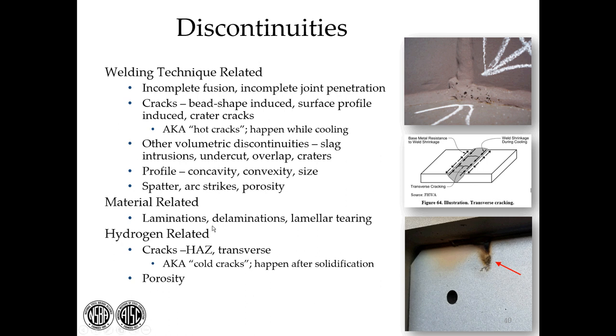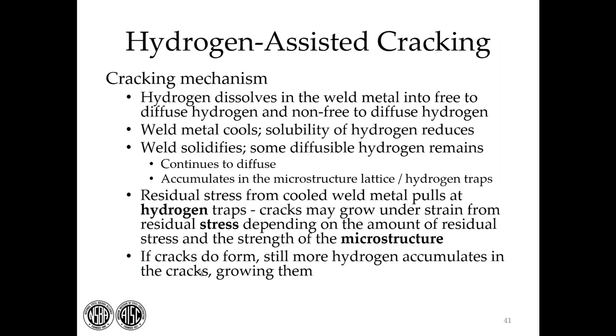And then finally, you have hydrogen-related problems, which can be porosity. Porosity can be from hydrogen. It can also be from other materials. You see it up here in welding technique as well. And then also hydrogen cracks, which are known as cold cracks. So hydrogen is a particular concern in welding. A lot of the practices in D1.5 are directed towards controlling hydrogen. So we'll go into a little more detail about what happens and how you get hydrogen cracking.